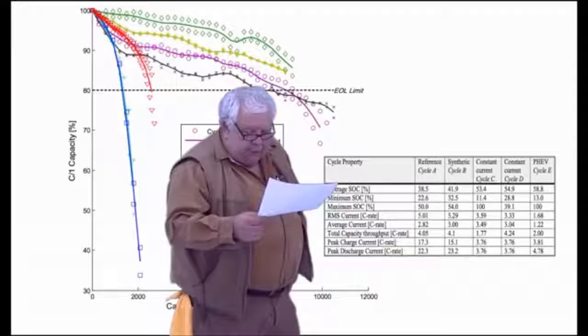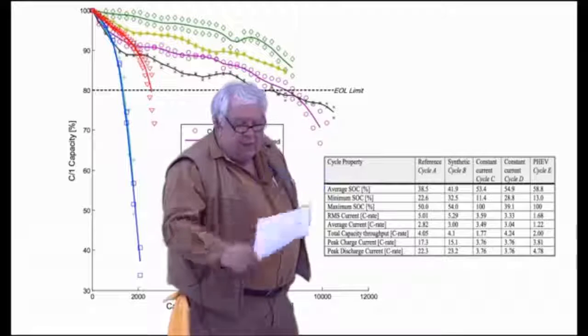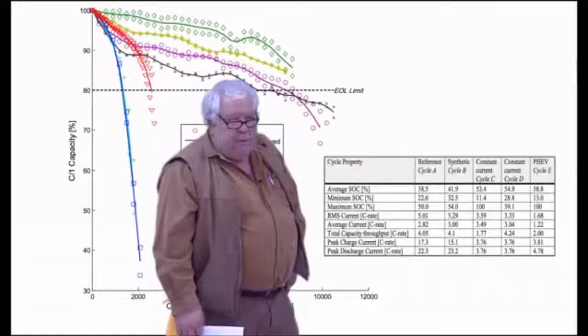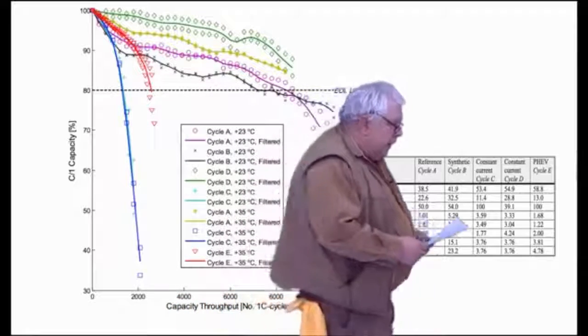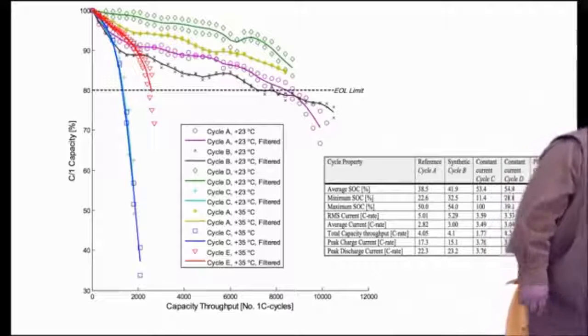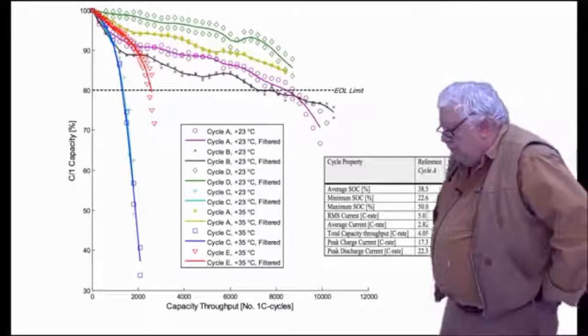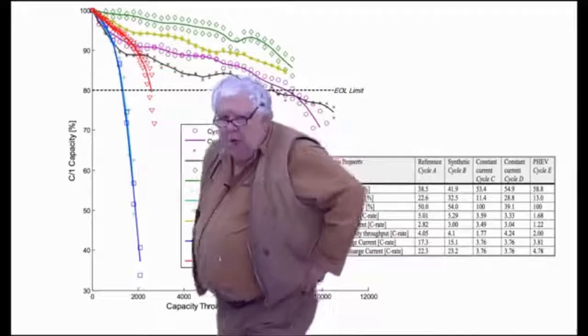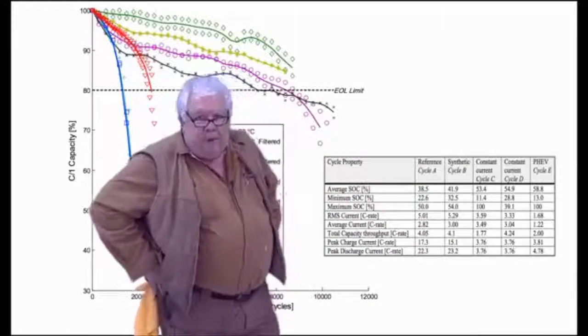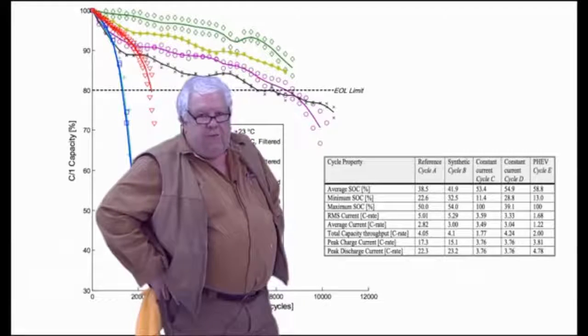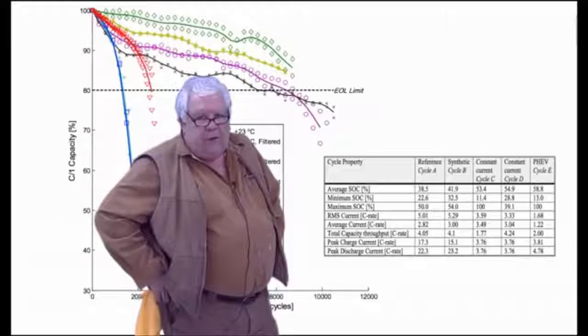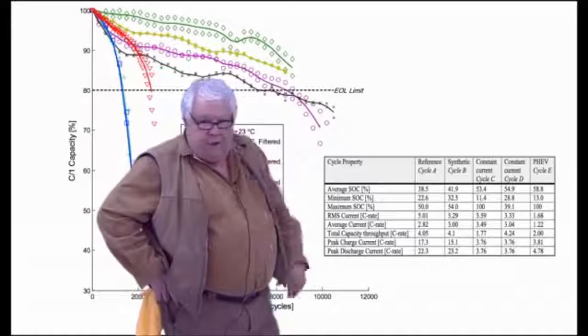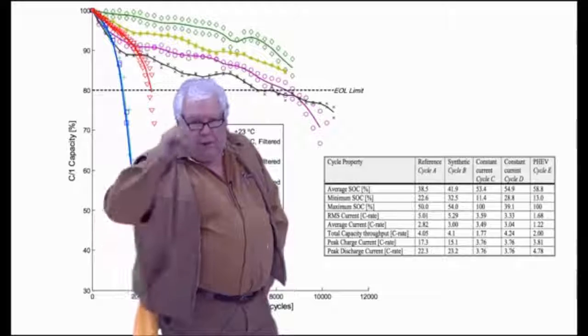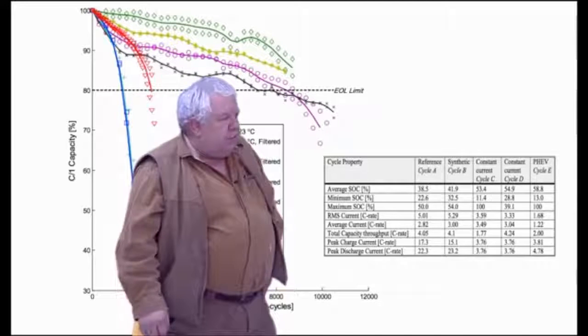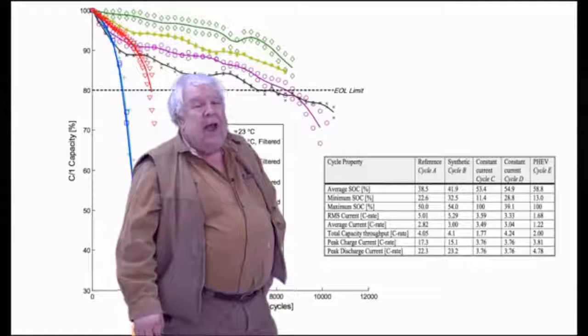Now, I will say that there is an extreme element in here, and that his maximum state of charge is 50%. And so it would appear that the dangers to cycle life are not temperature, and they're not the amount of current that you draw out of them. It is a function of the extreme ends of the charge and discharge cycle. I've said this for years. If you could charge it to 51% state of charge, discharge it to 49%, and then charge it again to 51% and stay in that range, they would last forever. According to Mr. Groot's study, I would say probably 3.5 forevers.